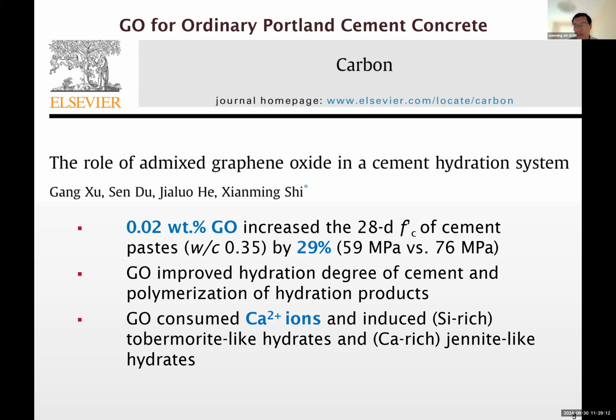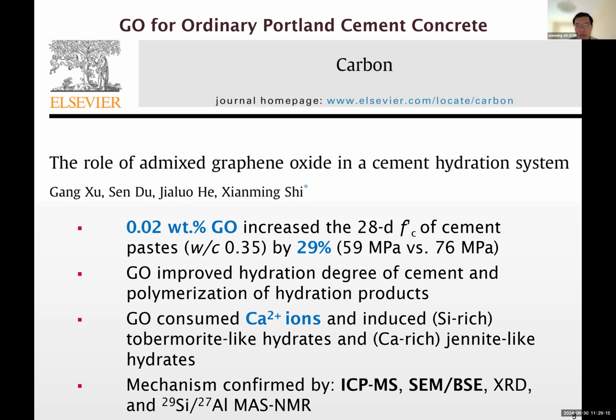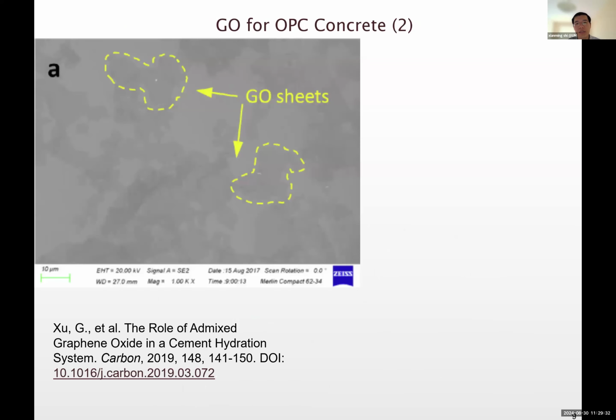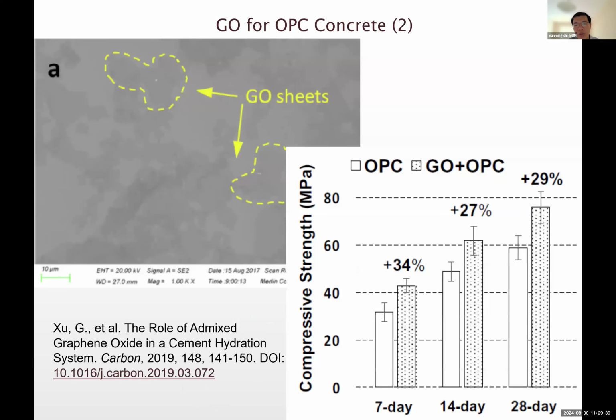tobermorite-like hydrates or jennite-like hydrates. So these mechanisms were revealed using a lot of different tools. I won't go into details here, but again, graphene oxide is a magic multifunctional admixture for ordinary Portland cement concrete systems. So we can actually see the nanoplatelets under the microscope. We see the strength improvement, and also we see improvement in durability. But now,